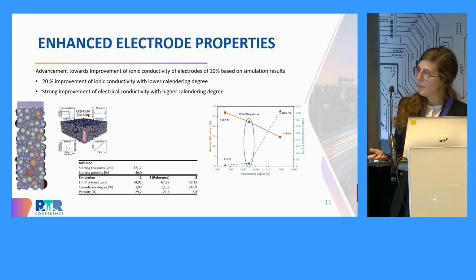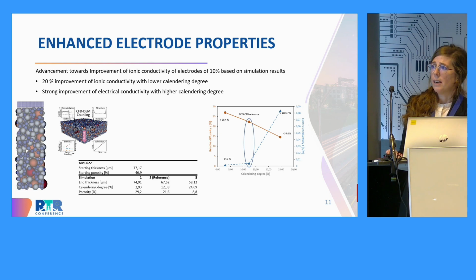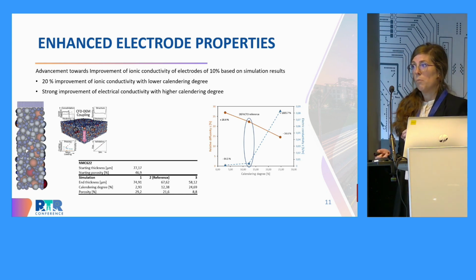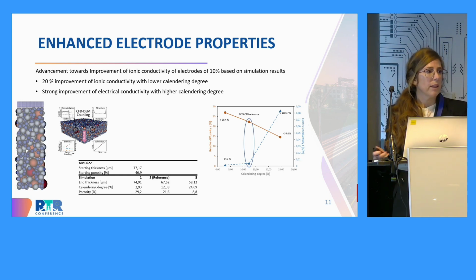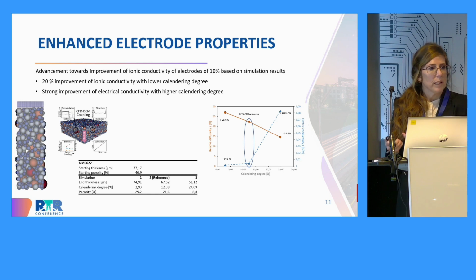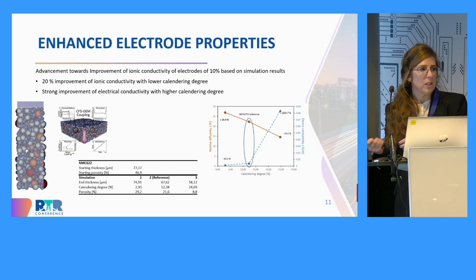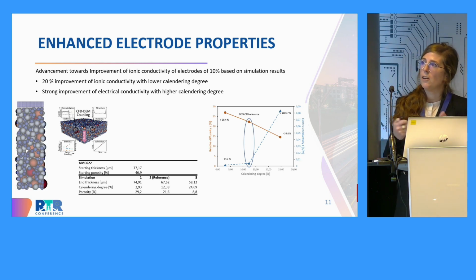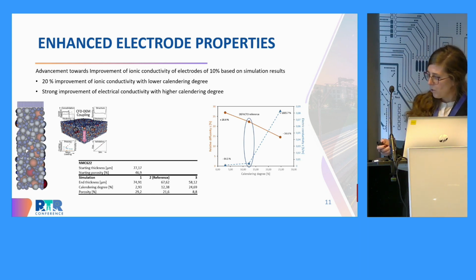Here what they are doing is capturing the calendering parameters' influence on the microstructure of the electrode, and then with mesoscale modeling on the cell performance, they were able to predict the ionic resistance or ionic contribution, as well as the electronic resistance. So this is, for instance, one way to link electrode fabrication together with performance. And if you know this information in advance, then you don't need to start modifying the conductive additive, because maybe the limitation comes from the ionic resistance and not the electronic resistance. So this was one of the samples.